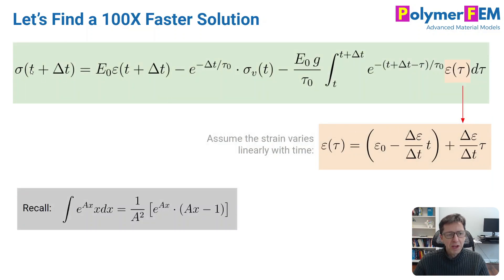Here's the equation again from previous pages. The stress at t plus delta t, this is the instantaneous response, here's the viscous response, and this is the final integral from t to t plus delta t. What do we do with this? Well, we can integrate anything that's an exponential function. The problem here is that the strain can be any function. In general, strain doesn't have to be any specific mathematical form. This has to be solved in some way for any strain, and the trick we will need to use here is to assume that the strain during this increment is linear. So the strain is somehow increasing or decreasing linearly in this increment, and every increment may be different, but in this particular increment, we need some kind of equation for this epsilon of tau. And here is what the equation should be.